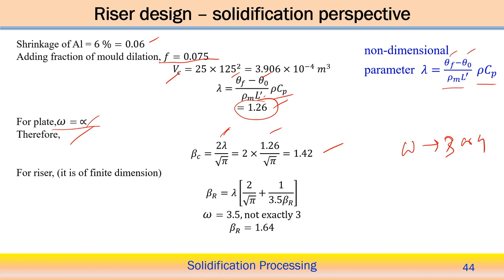So, beta r for the riser: lambda equal to twice by root pi, 1 by 3.5 into beta r. Lambda is already calculated, because it depends on the freezing temperature, the initial temperature, rho m L, and rho cp value. So, lambda will be the same in this case, but even so, we get a quadratic equation in terms of beta r. By solving the quadratic equation and taking the positive root, we get beta r equal to 1.64. We can see beta c for the cast volume is 1.42, but in the case of the riser beta equals 1.64. Both beta values we can calculate, but remember, this calculation takes care of the curvature effect associated with the casting process.